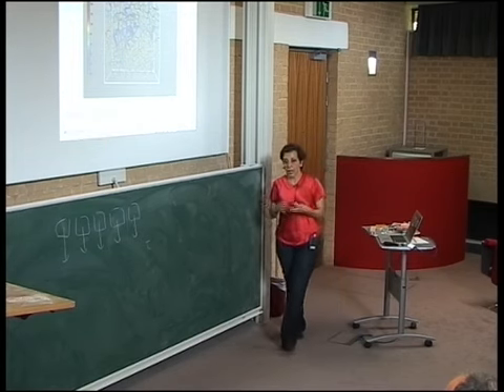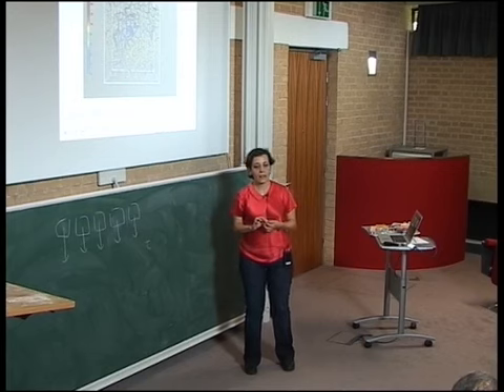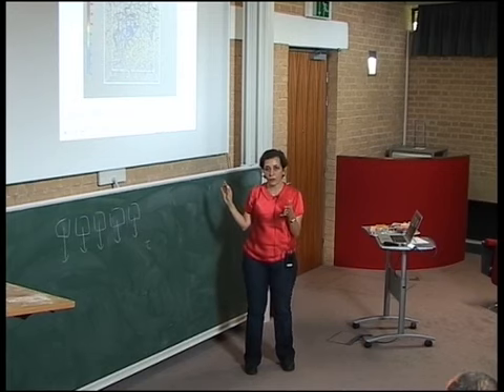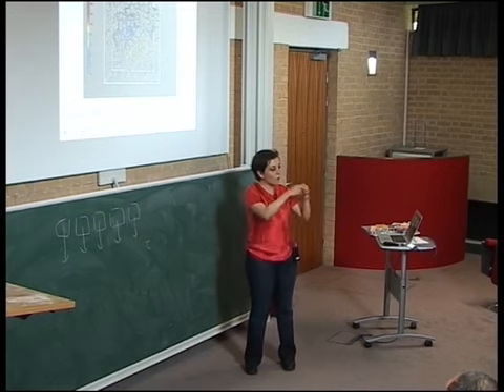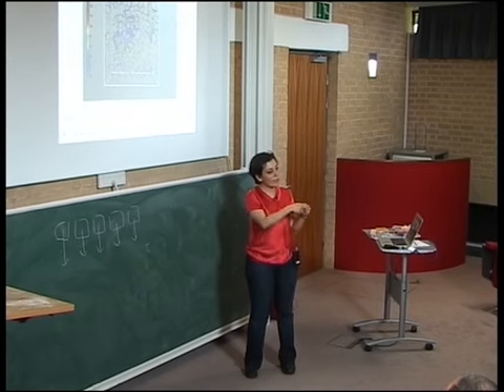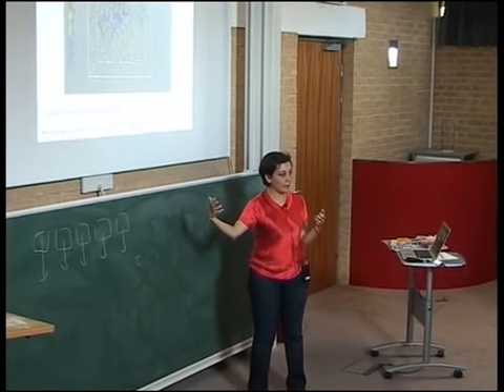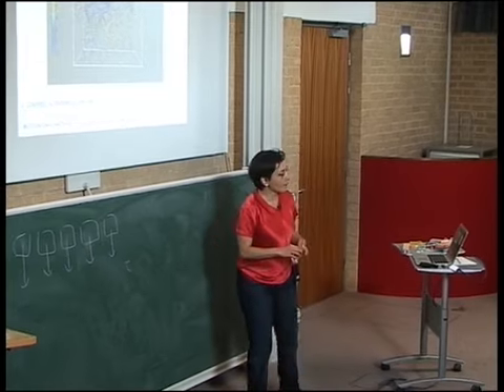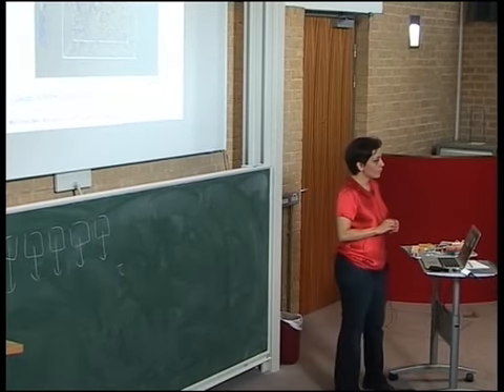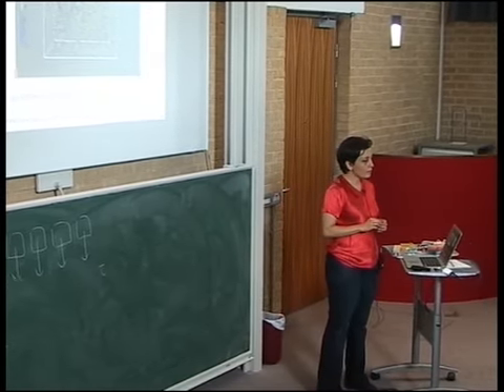On the other hand, what is interesting is that this tells you that the consequences of one single bond breaking can propagate far away in the network. It doesn't mean that there are other bonds breaking there. It means that you've got wiggling and flopping occurring in that region. It breaks here, then it flops over there. Yes, this is the idea. But in this change, do two particles come into contact? Yeah, they can, and so they can reform.